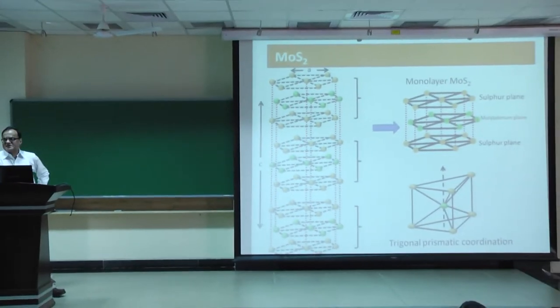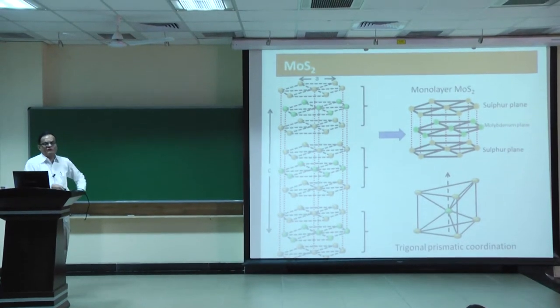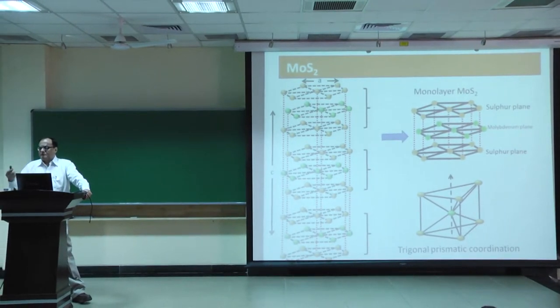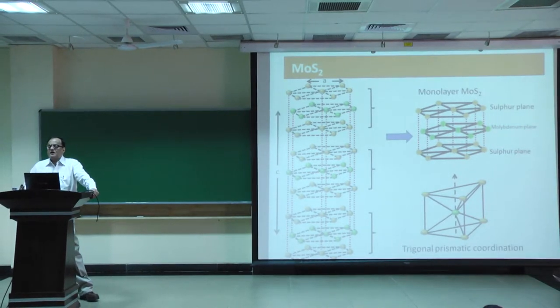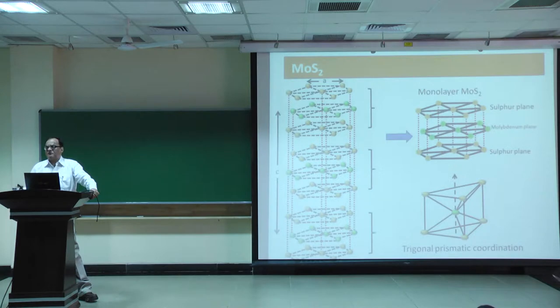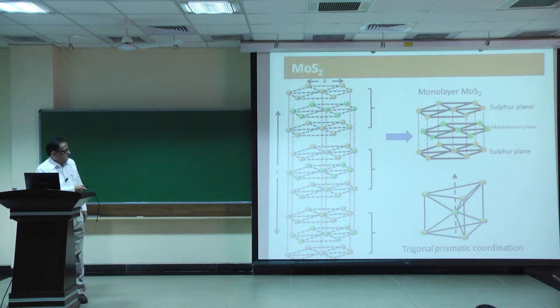The other system I will look at is molybdenum disulfide, which has three layers of S-Mo-S stacked in trigonal prismatic coordination along the C axis. The interest is to look at a single layer of MoS2 and see what is interesting compared to graphene. Graphene does not have a band gap near the Dirac point, which has implications for field-effect transistor on-off ratios. Molybdenum disulfide has a gap of around 1.5 eV and very interesting aspects of valley physics.